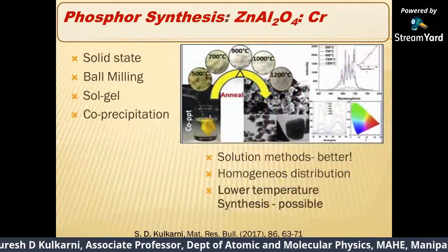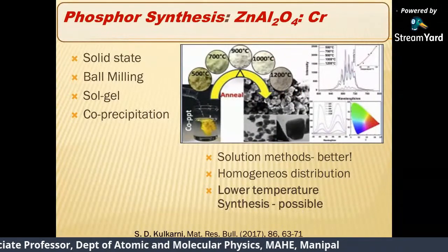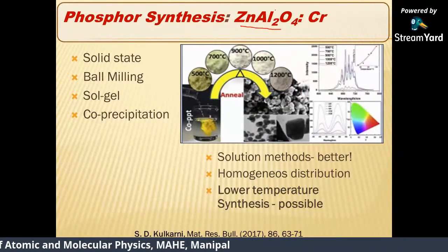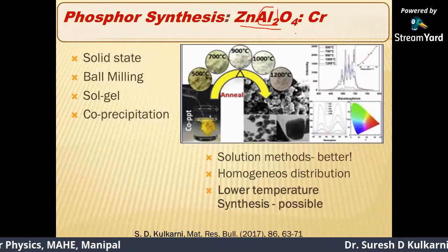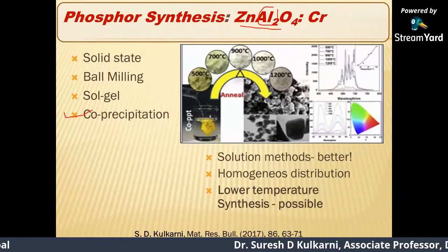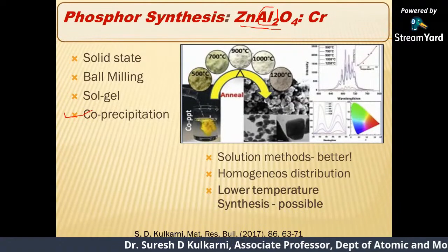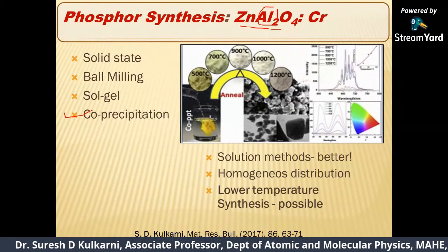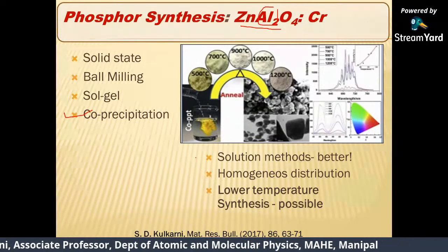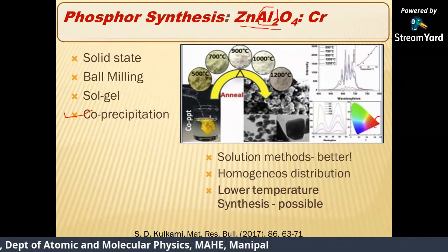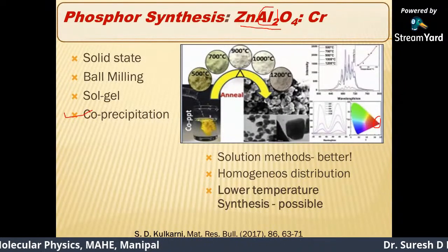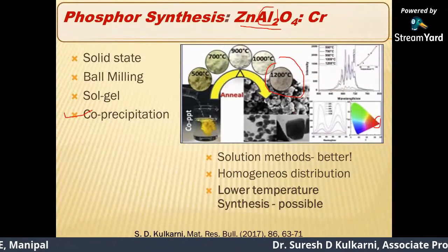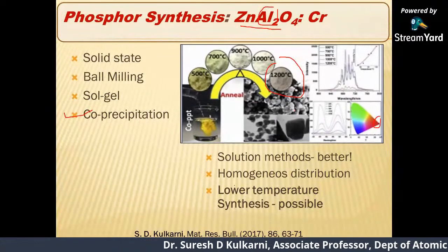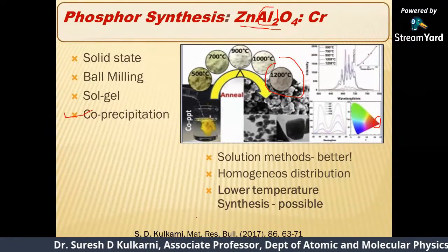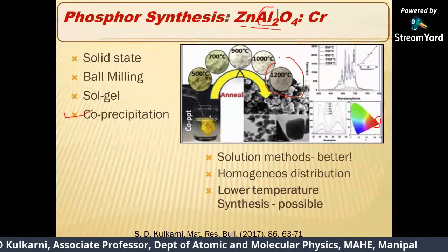Again, the same thing. Similarly with co-precipitation, we just changed the material. Now we use aluminum here, chromium doped zinc aluminate, and we use a co-precipitation approach. You can see we worked from 500 to 1200, and we see that the properties of the material, a nice red emission here, come only when you go to a higher temperature of 1200 degrees Celsius. The details can be found in our publications. But what to understand from this is there are two important observations.